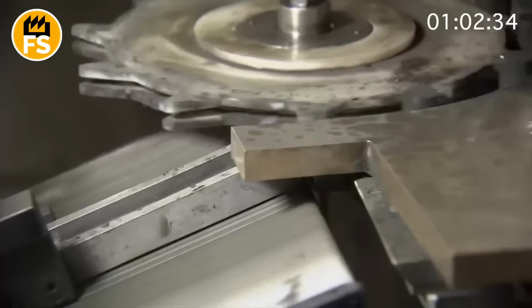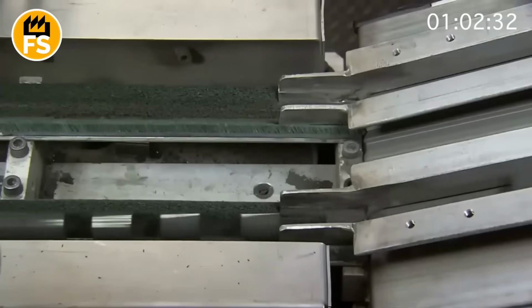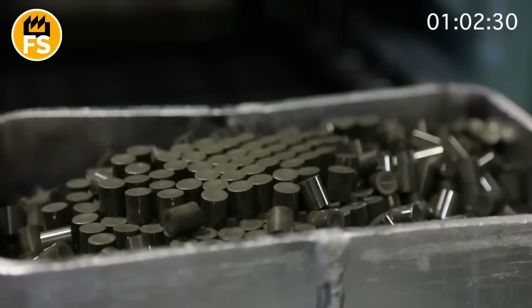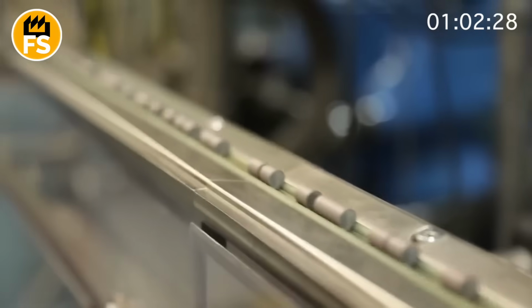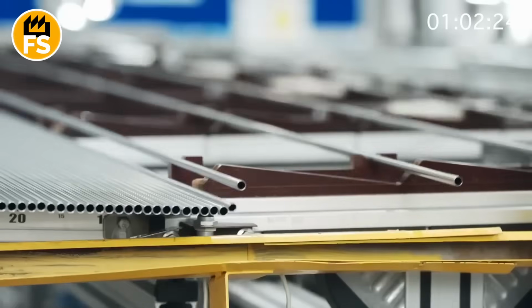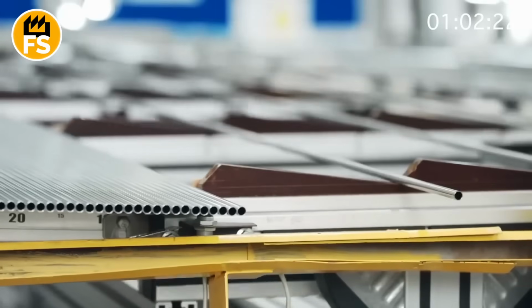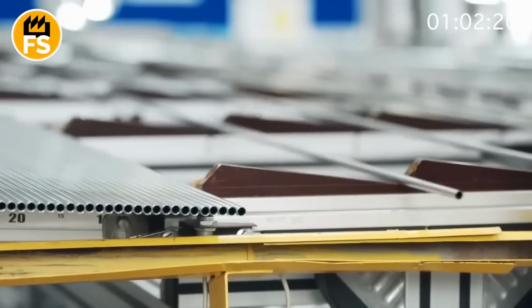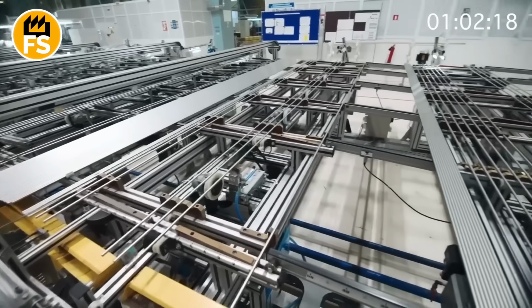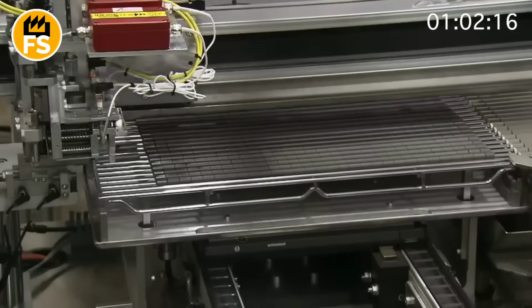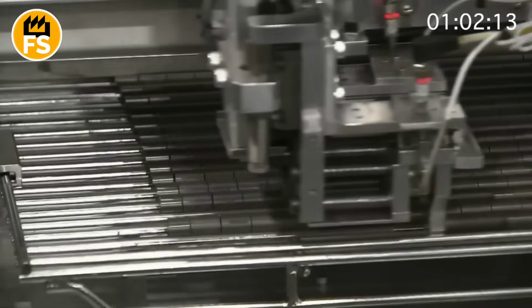natural gas. Next, the pellets are sintered in furnaces at almost 3,000 degrees Fahrenheit to make them strong, like porcelain. Then they are polished, ground. Perfect dimensions are important for a tight fit in the cladding. The pellets are placed in long metal tubes, fuel rods, usually made of a zirconium alloy, because it doesn't rust, doesn't react with water, and withstands insane radiation. Over 300 pellets are placed in each rod.